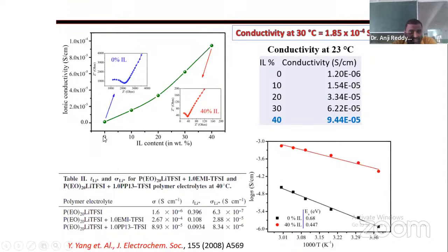If you increase the IL content up to 40%, the film is stable. If you increase the IL content more than 40, the mechanical property will reduce drastically. That's why we have not gone beyond 40% of IL. Up to 40% of ionic liquid in this PU-LiDFOB, the conductivity is good, and mechanically it is also good, not degraded that much. The conductivity we achieved at 23 degrees centigrade is 9.44 x 10^-5. At 30 degrees centigrade, we reach 10^-4.